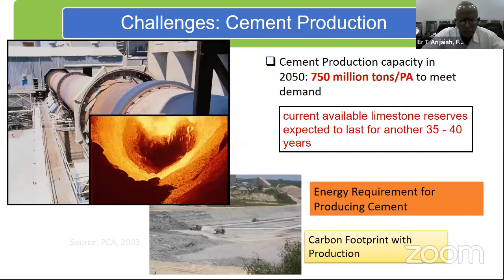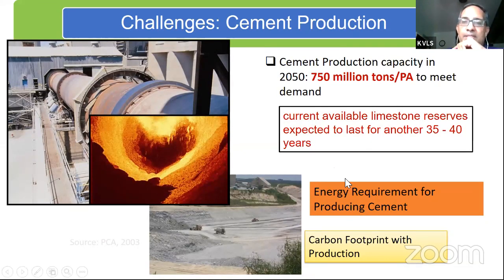So now, to meet the 750 million tons per annum demand, we need to be able to produce the raw materials which are needed. And one of the primary raw materials for cement production is limestone. Now, our current available estimates of limestone are only going to last us 35 to 40 years. It's very well known, which means that we may run out of limestone before we are able to produce all the cement that we need for putting our infrastructure in place.